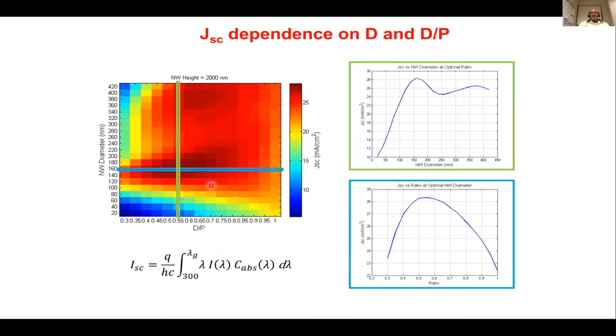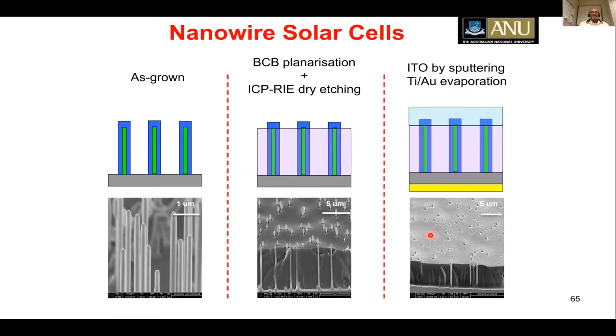Again, simulations show that you need the diameter of the nanowires to be around 150 to 160 nanometers, and the diameter to pitch ratio needs to be somewhere between 0.5 and 0.6 or so. Again, the simulations play an important role as a guide for the fabrication of the devices. So here are the nanowires which have been grown based on those designs.